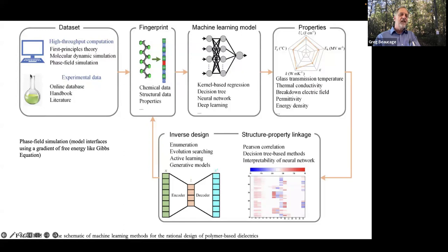In this case, when they're doing this dielectric work, it's absolutely a total mess. You can't trust anyone's data. It's all totally different units, and different machines used to measure it. So they go back and, as is a common way to do, run a simulation program to simulate these dielectric materials and certain aspects of them, especially the interface between the inorganic and the organic, because that's where the charge builds up. That's where you're storing charge, basically at the interface.